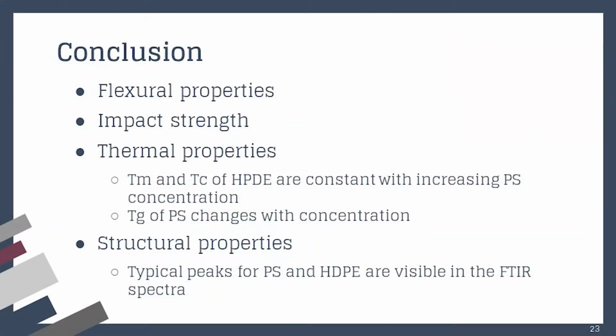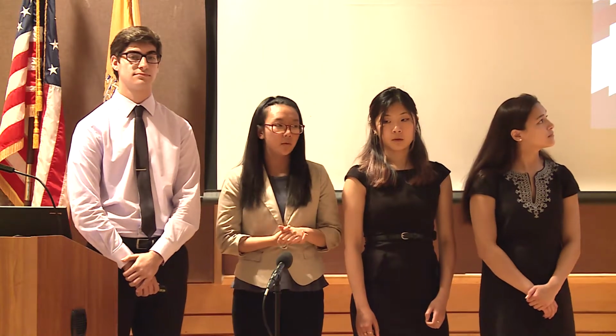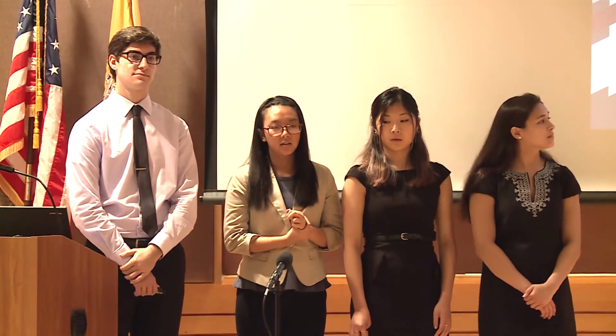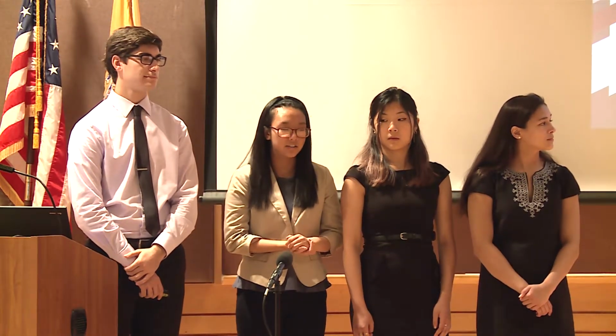So to conclude our research, we were able to hit upon the flexural, impact, structural, and thermal properties of our immiscible polymer blends by our 4 different tests. It's important to note that we want to do further evaluation of our impact tests to see why we had the 2 outliers. We also noticed that the thermal melting point and crystallization temperatures were consistent with our increasing polystyrene, and we also noticed that the blend of the 80 polystyrene HDPE had the greatest toughness, and our FTIR results gave us the accuracy we needed of confirming what our blends were composed of.